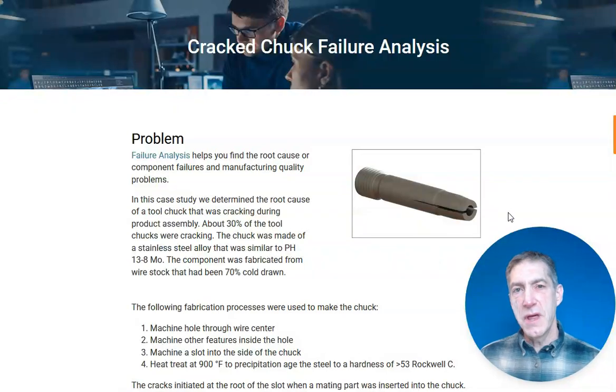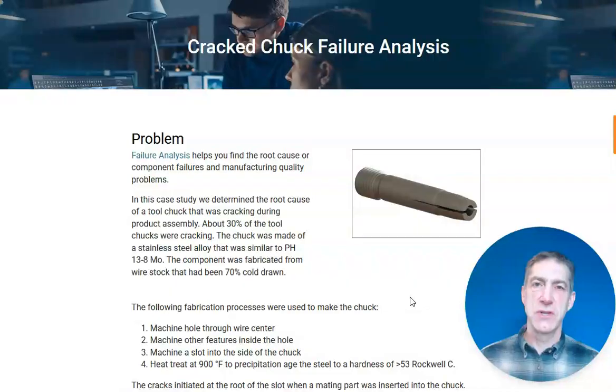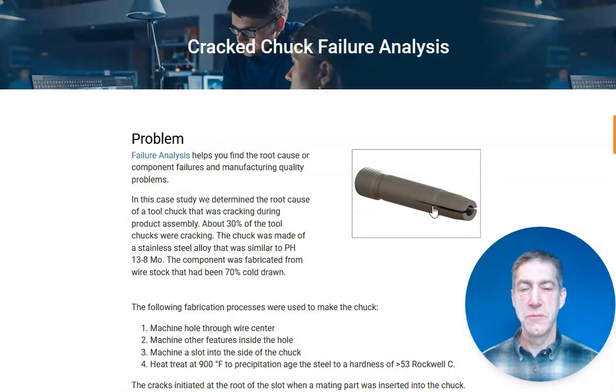After the heat treatment, there was subsequent processing, and during the subsequent processing, the chucks were cracking. There was about 30% fallout. So there was a lot of money being put into these chucks, only to have to throw out 30% of them because of the cracking after the heat treating. And the cracks were forming at the end of the machined slot.